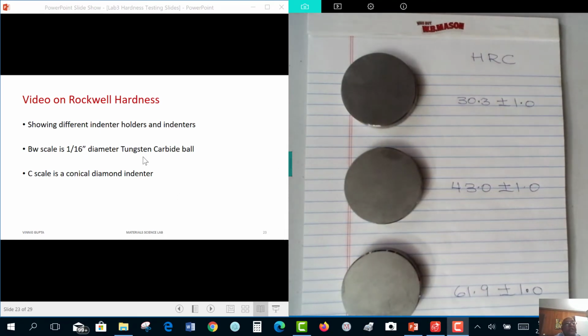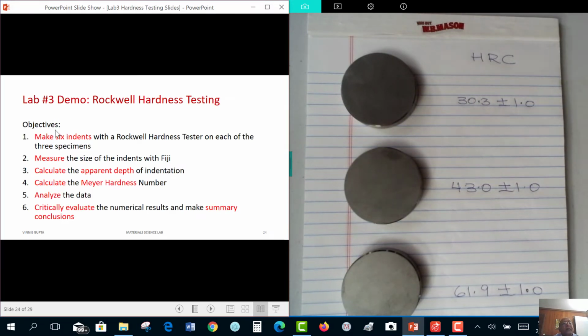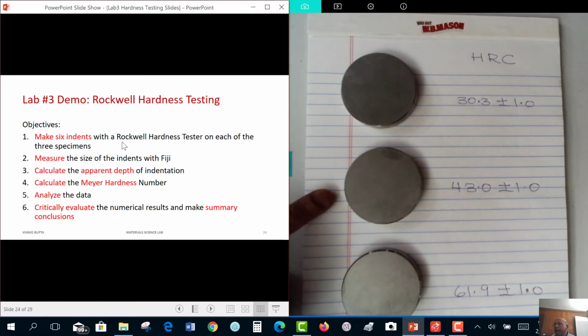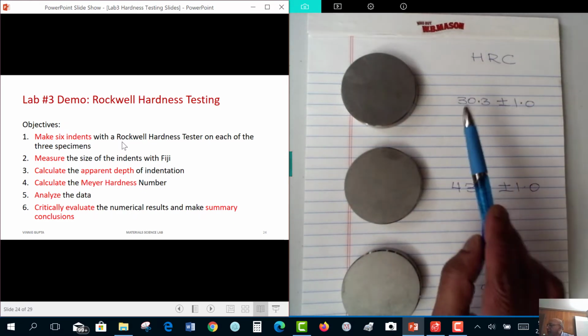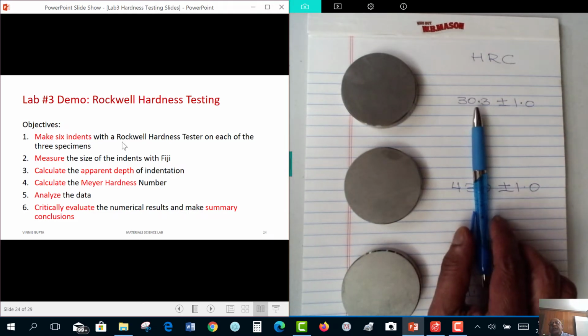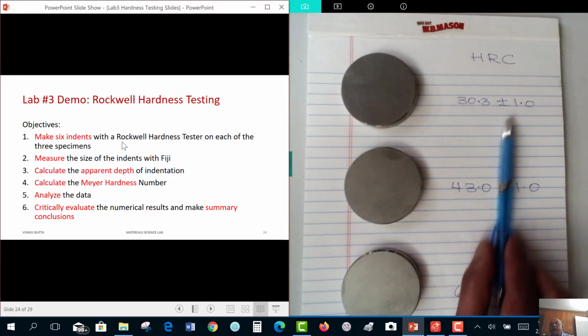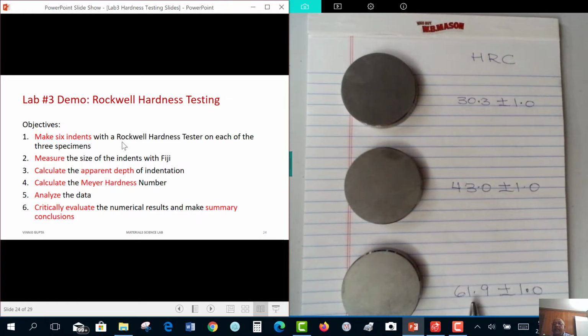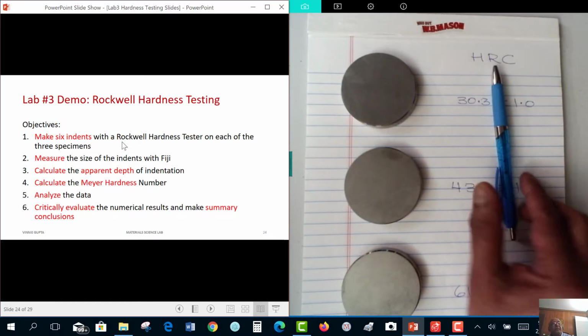Okay, we are going to be working on steel, so we are going to be using C scale, which has a conical diamond indenter. So let's look again at what we are going to do in this demo. We are going to do Rockwell hardness testing. I have got 3 specimens here. These are really extruded, but I keep calling them cold rolled because that's typically the terminology sometimes used. They have three different hardnesses. So the specs are 30.3 plus minus 1, 43 plus minus 1, and 61.9 plus minus 1. Again, hardness, Rockwell C scale.